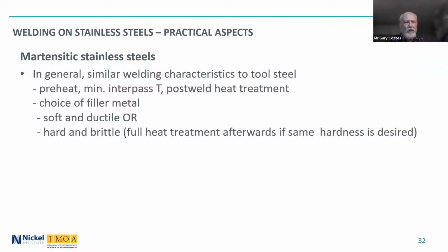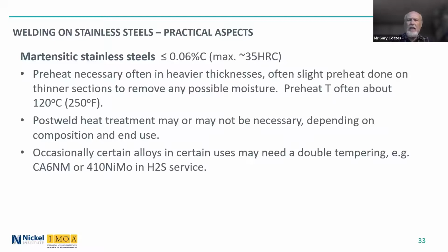You want to do a preheat, minimum interpass temperature. You want to keep the interpass temperature high. Post-weld heat treatment is often needed. You have the choice of filler metal, soft and ductile, or hard and brittle, unless you do a heat treatment afterwards. The ones used in the oil and gas industry generally are the low carbon ones.